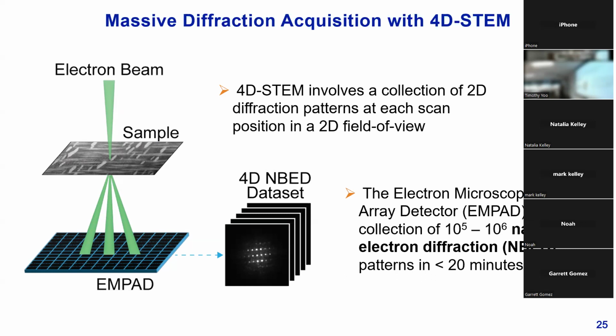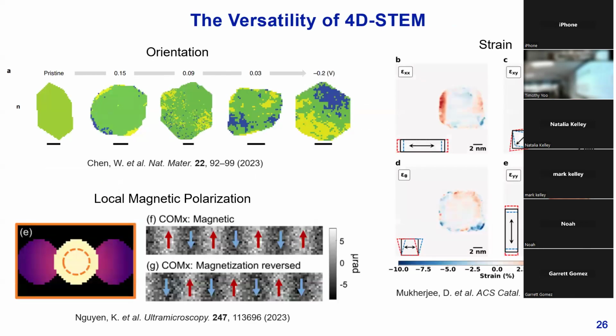which enables the collection of tens to hundreds of thousands of diffraction patterns, in this case, nanobeam electron diffraction patterns, in a matter of minutes. And so now we've already solved the problem of acquiring tons of diffraction data of high quality in a very efficient amount of time. And we can see that historically, other groups have used 4D STEM in a wide variety of ways. And so the versatility of this technique is really clear.